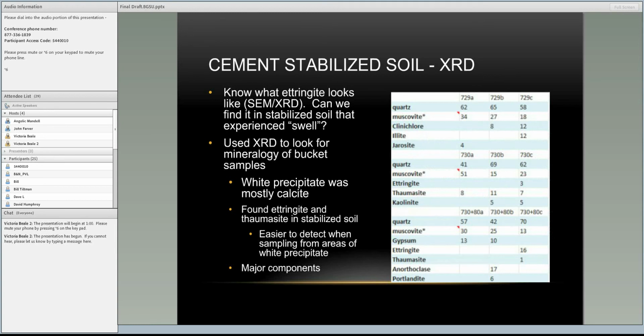With the cement stabilized soil that I had and just the samples that I looked at, for some reason 729 did not have as many needles as the other samples. It was primarily soil, but we did find evidence of ettringite needles in there. But a lot of the samples look like this on the left, where you're seeing mostly soil, but you will get areas where you can see ettringite needle growth starting.